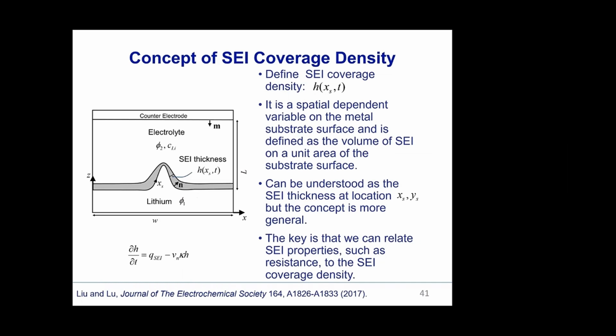We developed a model for concurrent dendrite growth and SEI growth on top of it. First, I will introduce the concept of SEI coverage density, H, as a function of X along the material surface. It's defined as the volume of SEI on a unit area of the substrate surface. SEI coverage can be understood as the SEI thickness at location X. But the concept is more general. The key is that we can relate SEI properties such as resistance to the SEI coverage density. The SEI growth is described by its electrochemical reaction.